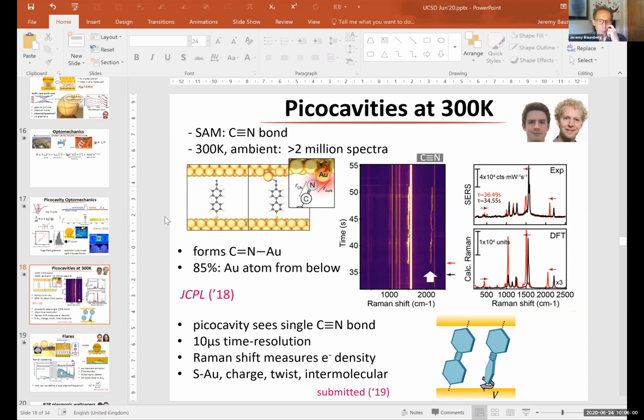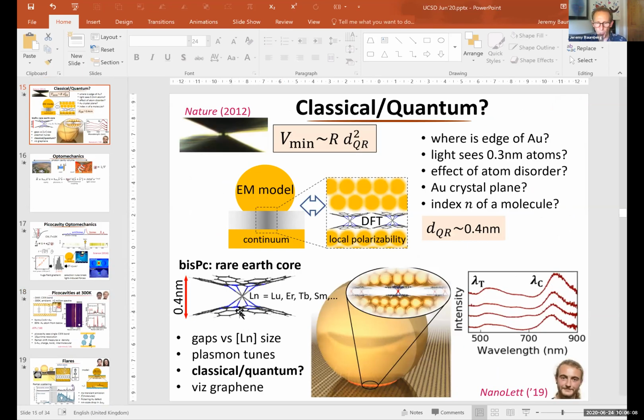So the problem is that when you're making gaps that are now a nanometer, or we even made, here we have some molecules I was going to show you, this is a bisphthalocyanine molecule that we're using, where the gap is 0.4 nanometers. And we have a rare earth in here. We can change many rare earths in the gap here.